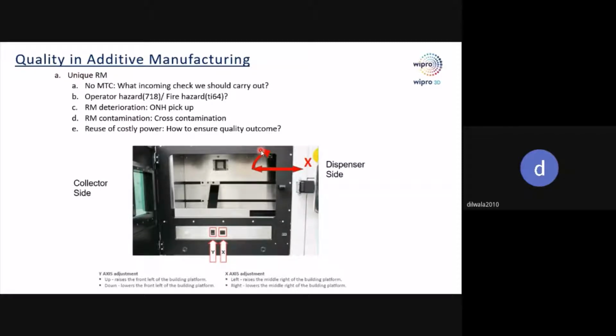And if that happens, basically you're creating a powder which cannot be used for subsequent builds, and these powders are pretty costly. Just to give you a reference, a stainless steel which you may buy at 220 rupees a kg, for a similar type of SS powder you have to pay almost 10 to 15 times higher price per kg. So powder should not be wasted anywhere.